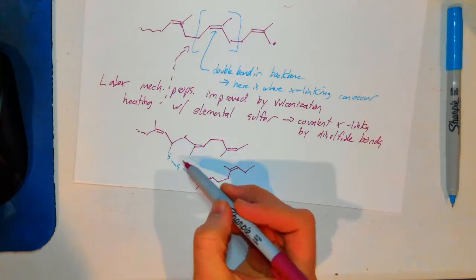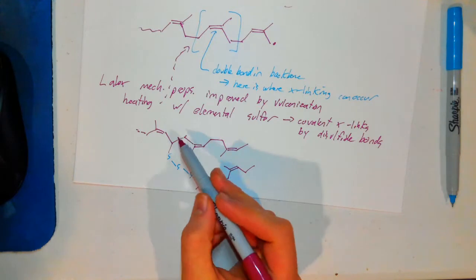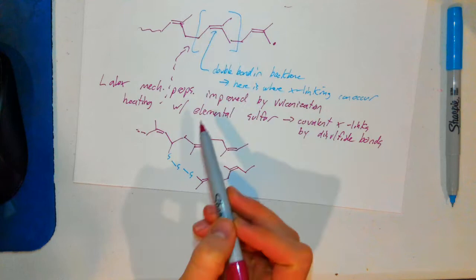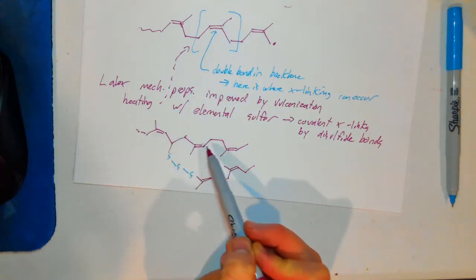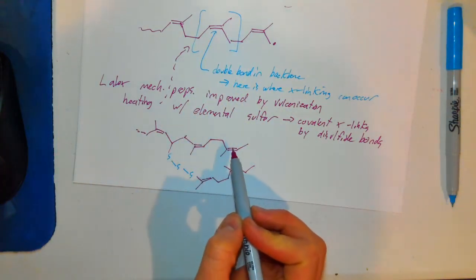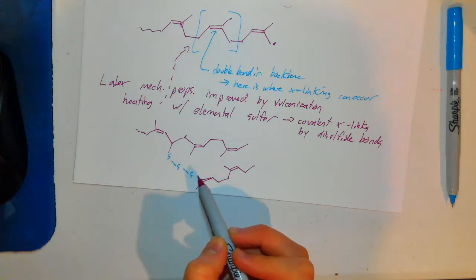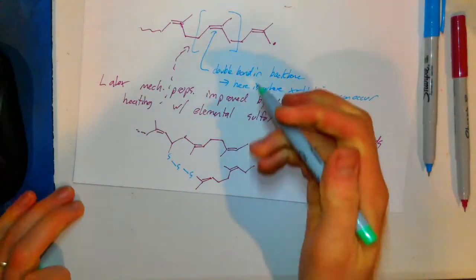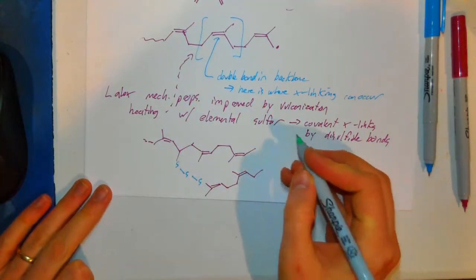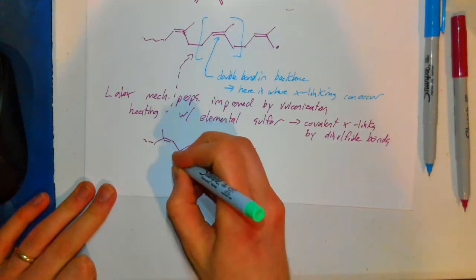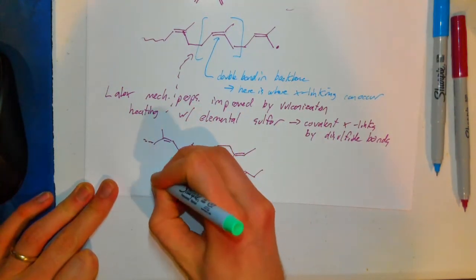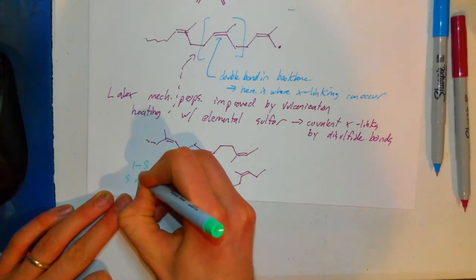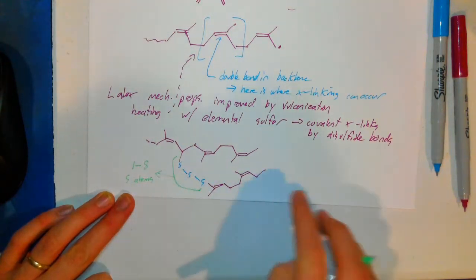So basically what happens here is the sulfur atoms, in the presence of heat, can crack open part of the chain. Most of the chain remains intact with a covalently bound backbone right here, but this also creates these covalent bridges between chains. And it turns out that, depending on exactly the temperature, times, and concentrations that you use in the vulcanization process, this can be somewhere between 1 and 8 sulfur atoms that participate in this bridge.